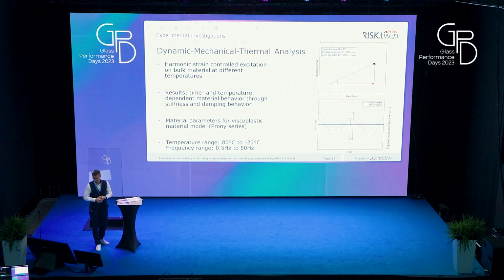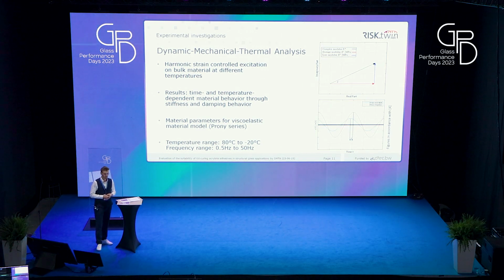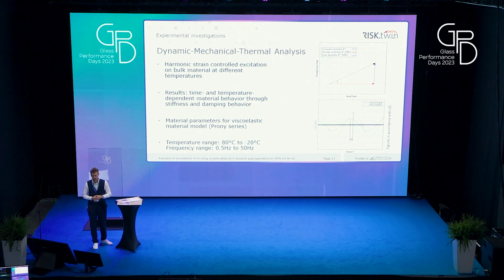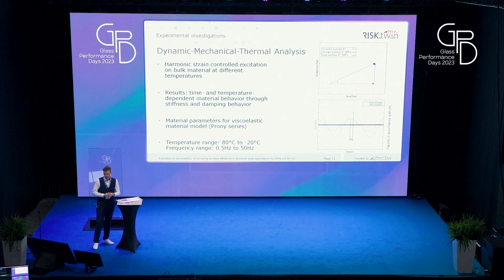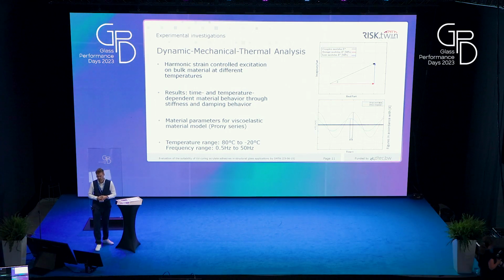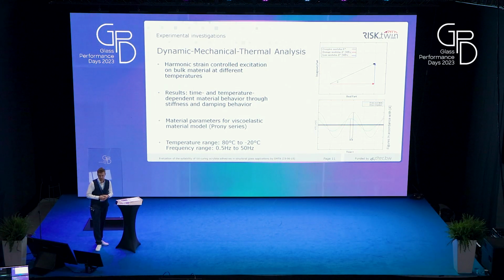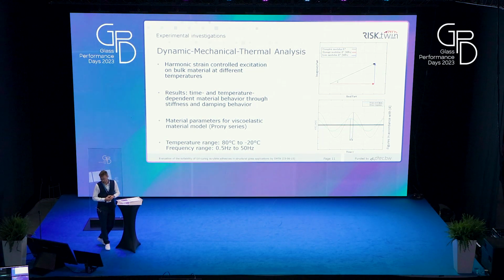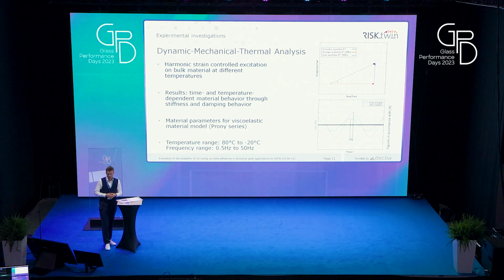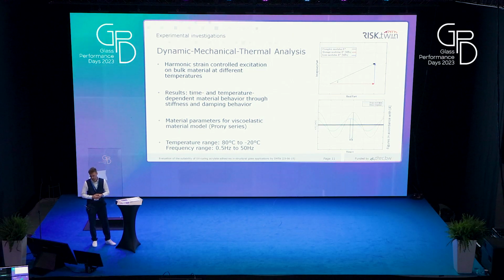What do we actually do in this test? We apply a harmonic strain controlled excitation on the bulk material at different temperatures. So in our tests, we started at 80 degrees Celsius and tested the adhesive in a logarithmically scaled distribution from 0.5 hertz to 50 hertz in frequency, and repeated that every 5 Kelvin until we reached minus 20 degrees Celsius. And as a result, we obtained a time and temperature-dependent material behavior, resulting in the so-called Prony series for our viscoelastic material model.